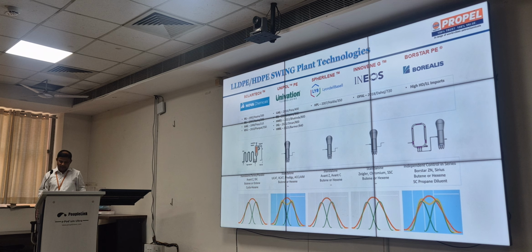And Spherilene, Haldia has the Spherilene technology. The drawback with this technology is that the color index is very poor as compared to Univation and Nova. INEOS also, Opal has started in 2018, 720 kT capacity. The Ziegler, chromium and single site catalysts can be used, but in their license Opal doesn't have that license. And Borouge has these technologies, where the loop reactor in combination with fluidized bed reactors, butene, hexene and the single site catalyst can be used for such applications.